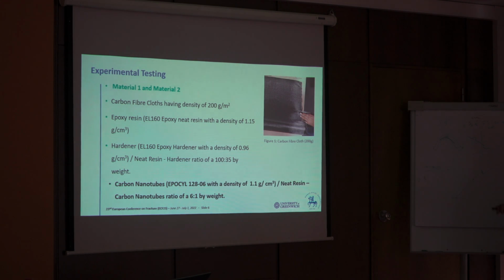So yes, we used the epoxy neat resin for all the manufacturing, and it is EL160 neat resin with a density of 1.15 gram per cubic centimeter, and then we used the hardener of the same brand, with a density of 0.96 gram per cubic centimeter, and the hardener ratio was 100 to 35. So this is what we used for material 1 and material 2, without carbon nanotubes.